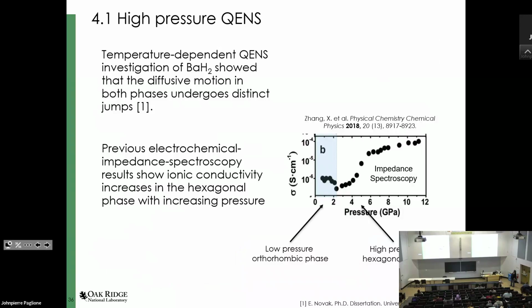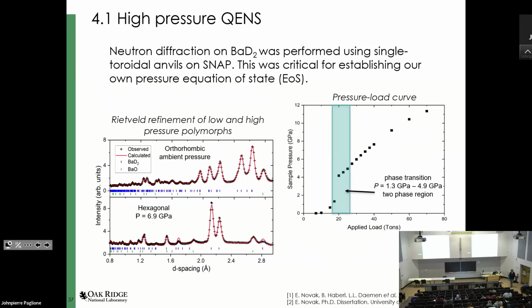So this here is the previous high pressure work that spurred our neutron scattering experiment. There were some observations from impedance spectroscopy that showed that the high pressure polymorph may actually be advantageous. This is something we were trying to understand and where we thought we could get to that pressure regime, and it was a good opportunity to push this capability and see what we can do. First things first, we need to make sure we actually get to the pressure we are interested in. When you are using a Paris-Edinburgh cell, you again don't have any optical access to measure pressure. So the only way you can first estimate the pressure is based on some pressure load curves that have been established for other samples,